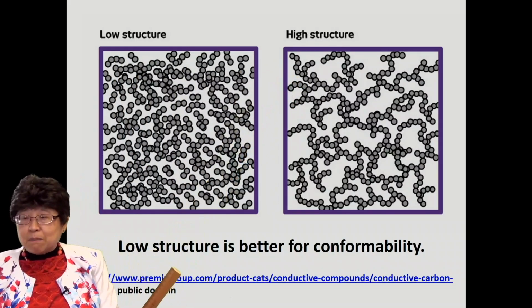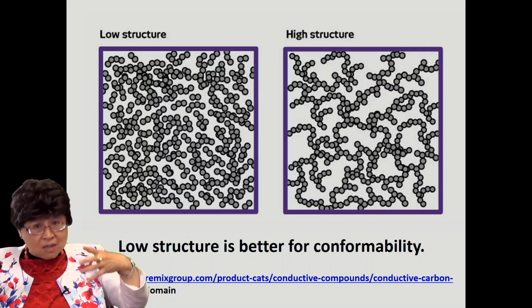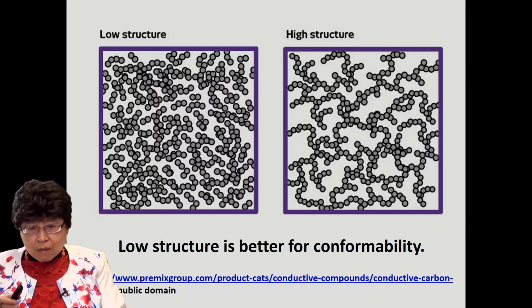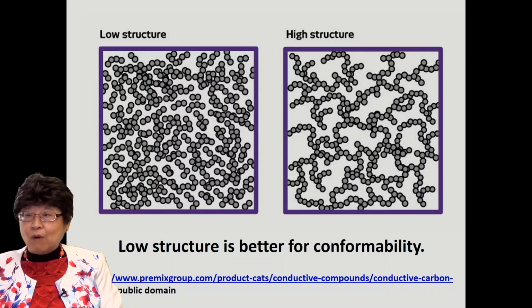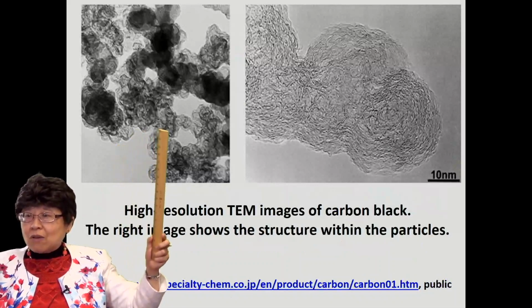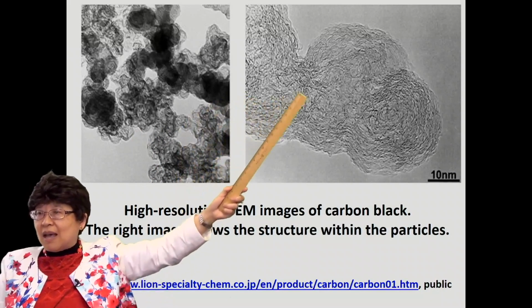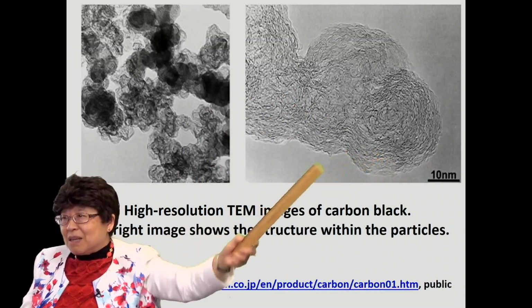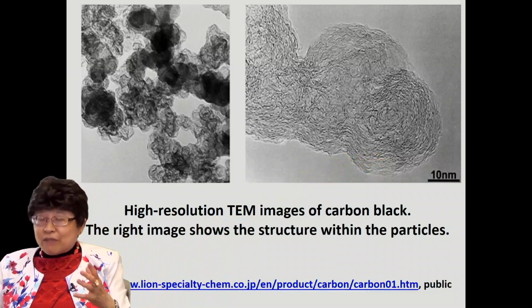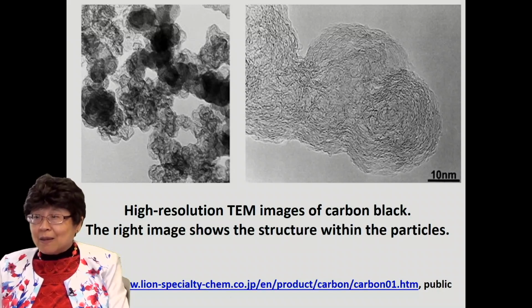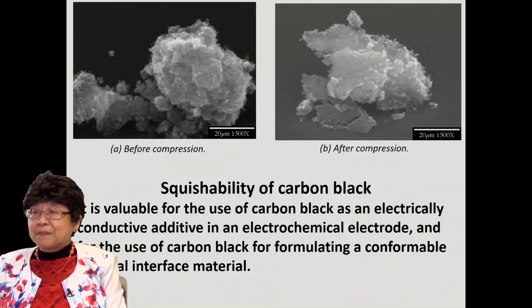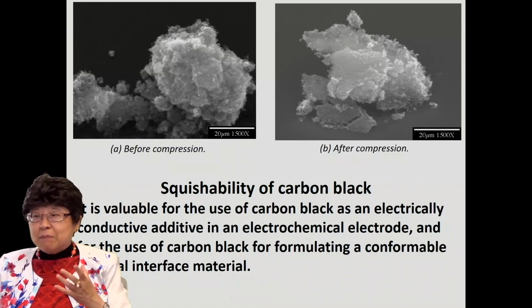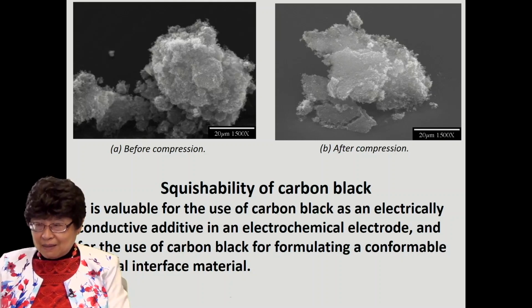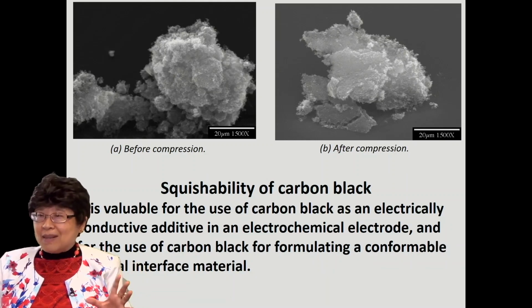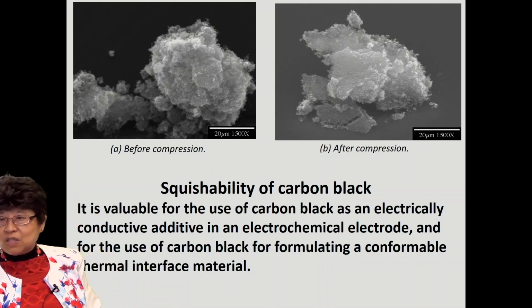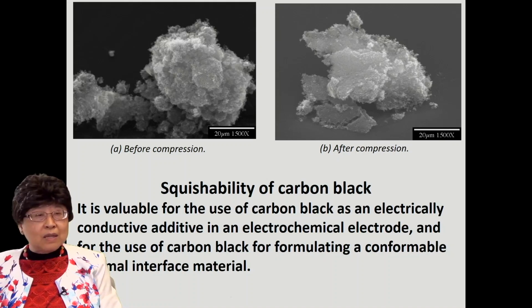And it turns out the low structure is better for conformability, because if you have a big one, it's harder to get into the valleys in the surface topography as needed for conformability. If you look at the carbon black under high resolution, one sees that there are some carbon layers, but not very well ordered, but there are carbon layers there, a certain degree of crystallinity. And as I already mentioned, carbon black is great in the squishability. And no other carbon has that degree of squishability. And because of the squishability, it is useful as a thermal interface material.